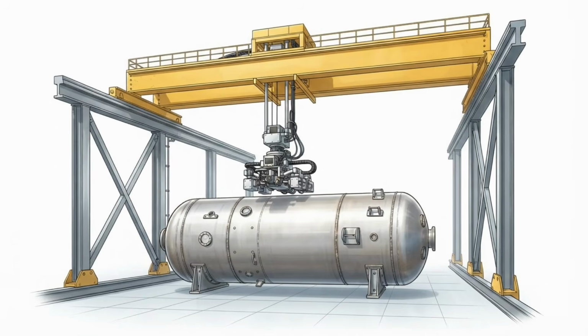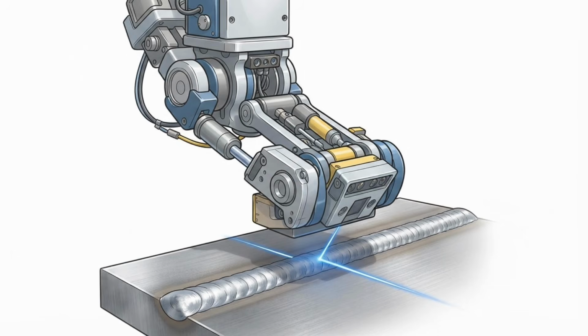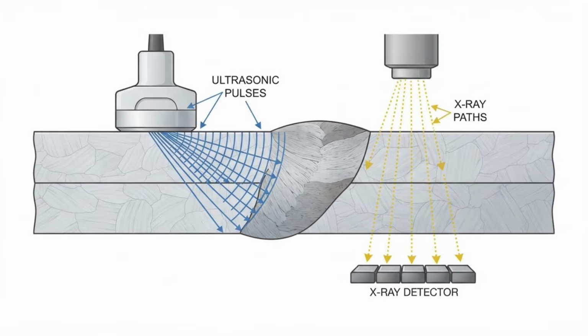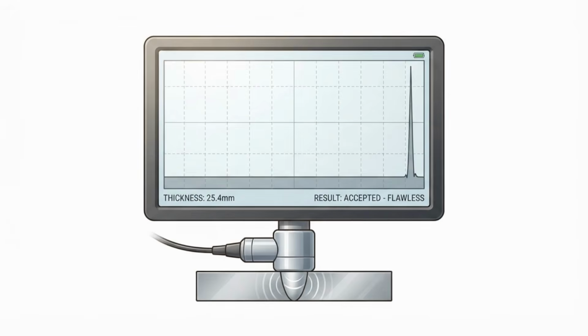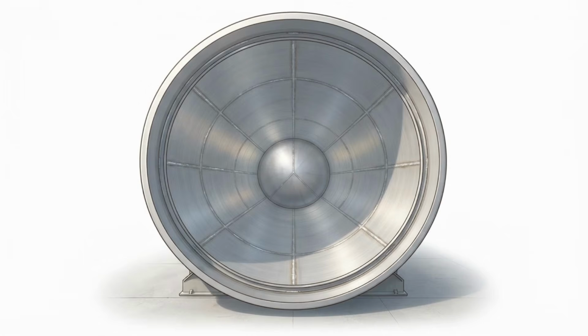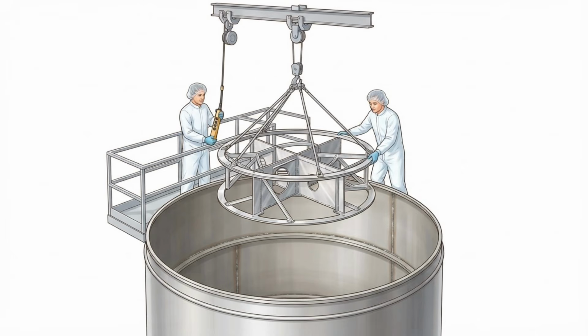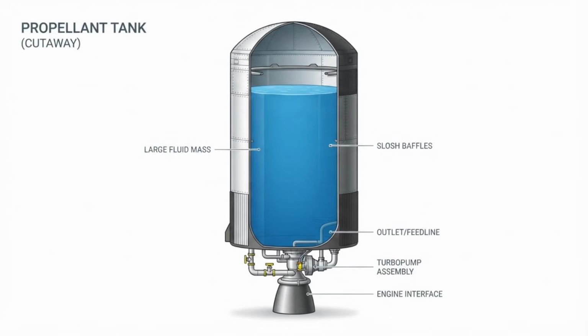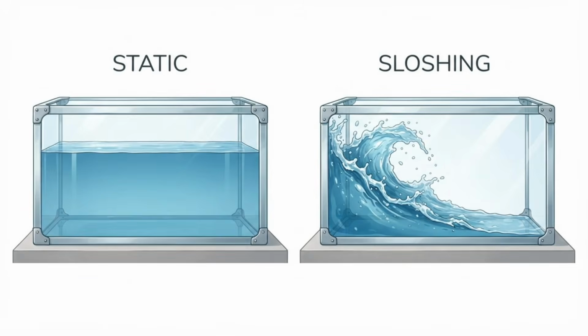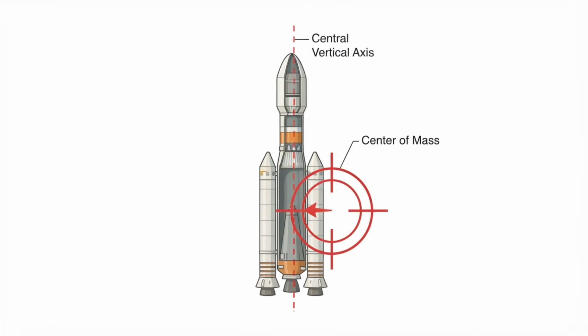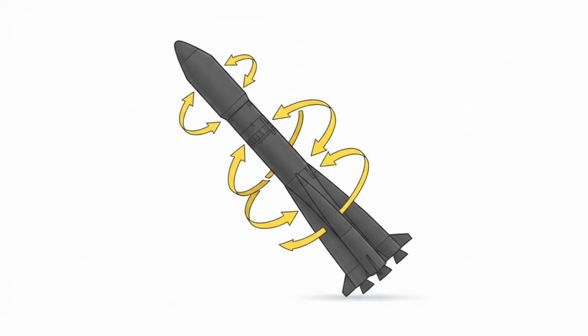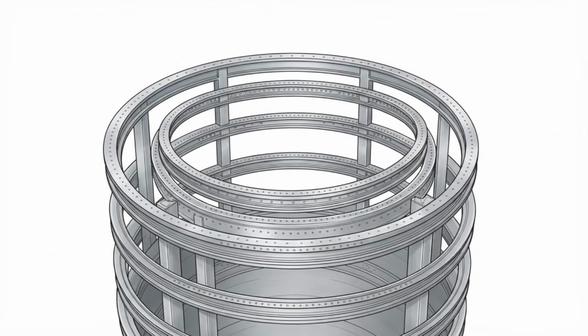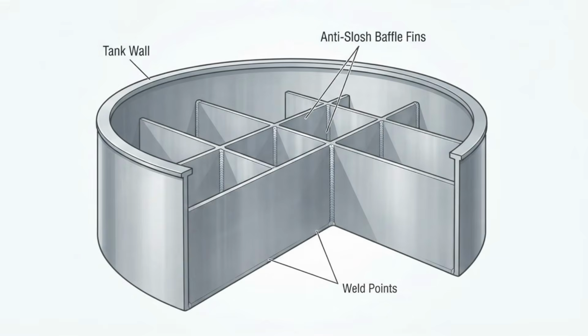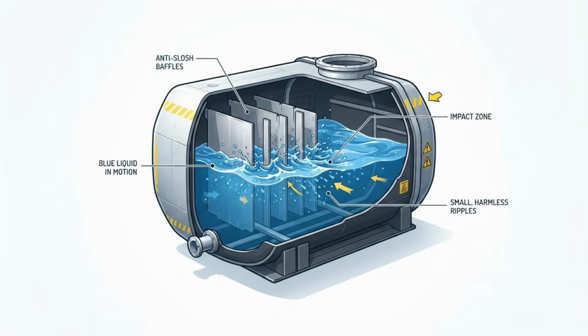Following the welding process, automated non-destructive testing machines scan every millimeter of the seam using ultrasonic waves and X-rays to ensure there are no internal voids or microscopic cracks that could tear open under pressure. Inside these massive tanks, manufacturing continues with the installation of anti-slosh baffles. During flight, thousands of gallons of liquid propellant can surge from side to side, creating a shifting center of mass that would cause the rocket to tumble out of control. To prevent this, lightweight metallic rings and intersecting fins are welded inside the tank walls to break up fluid motion and keep the propellant stable.